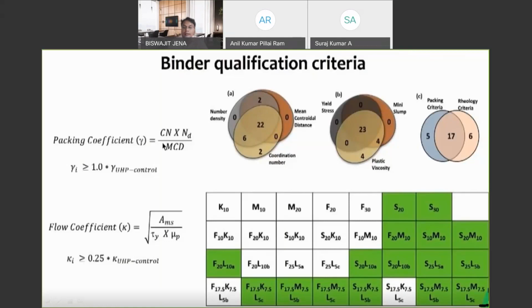The third one is the mean centroidal distance, the distance between a cement grain and like or unlike particles. The closer they are, the better the packing, which means the smaller the distance, the better the packing. So I put that in the denominator. So now I get a packing coefficient, which is the combined effect of all these three things: number density, coordination number, and mean centroidal distance. Again, we get a packing fraction, and my packing fraction has to be greater than the packing fraction of a control mix that has only cement, just to have some kind of comparison.